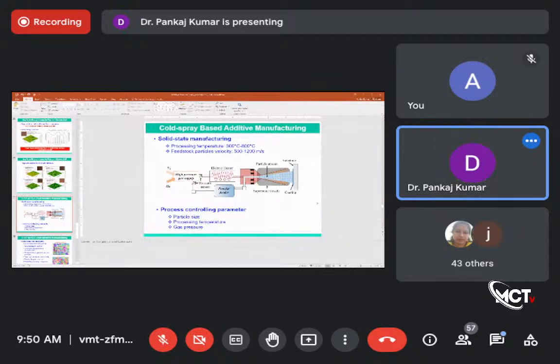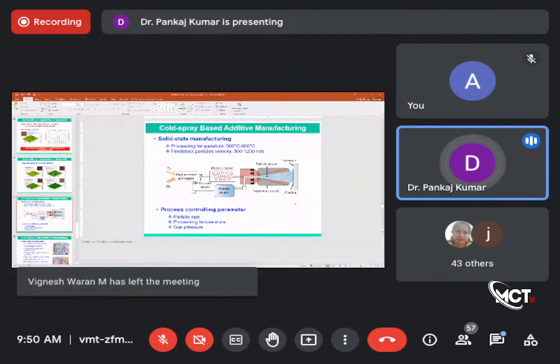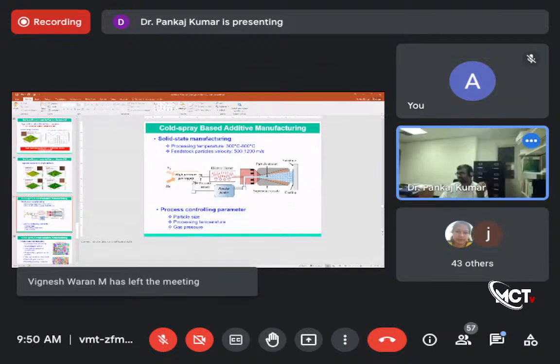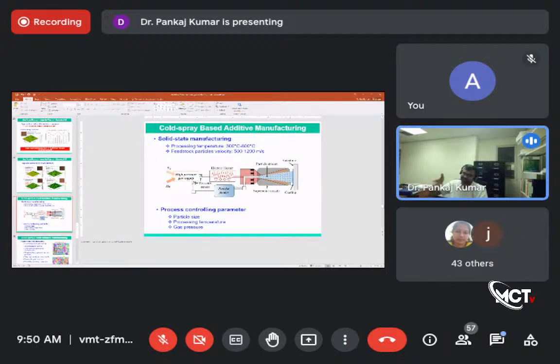To overcome that, people explored different ideas and came up with solid state manufacturing techniques, where you don't melt the particles. You start with the powders and you don't melt them. This is the cold spray based technique. People also sometimes call it supersonic deposition. Essentially, you accelerate the particles at very high speed, and they deform at the interface and form a layer, and you keep continuing layer by layer to make your 3D component. The controlling parameters are particle size, processing temperature, and gas pressure.